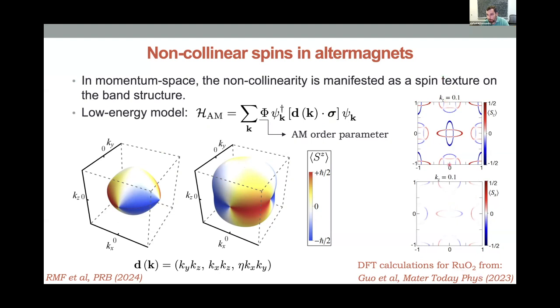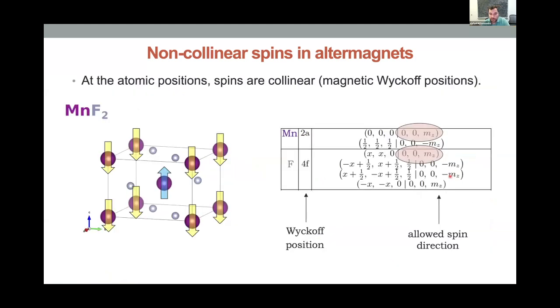They show that the moment you turn on spin-orbit coupling, you also get an X component of the spin away from k is equal 0. Now, you may say, okay, but that's good, but how do I understand that from a real space perspective? Especially because, let's take manganese difluoride. I can just look at the table of the magnetic Wyckoff positions, and I see that the spins in the manganese atoms have to be just collinear, pointing along Z, for that magnetic space group. Even in the fluorides, they have to point along Z. So where is this non-collinearity I'm talking about?